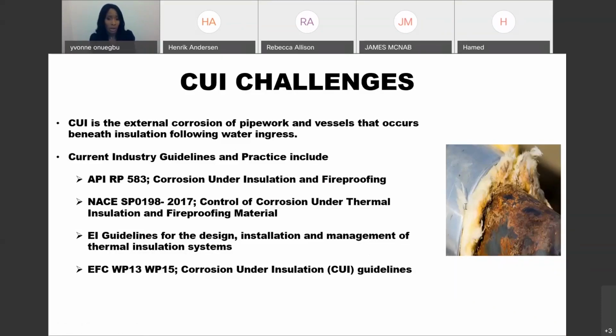And if we are looking at our corrosion resistant alloys, you can get CUI from 30 degrees centigrade up to 200 degrees centigrade. And I must say that the manifestation of CUI in corrosion resistant alloys is in the form of stress corrosion cracking or chloride pitting. If we pick on the contaminants, they increase the conductivity or the corrosiveness of the water environment. These contaminants, so I'm talking about your chlorides and your sulfates, can be external to the insulation or they can be leached from the insulation.